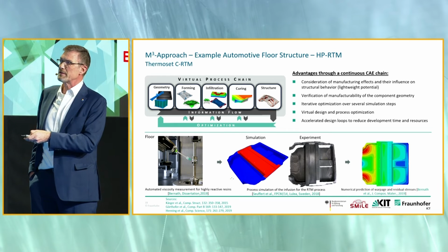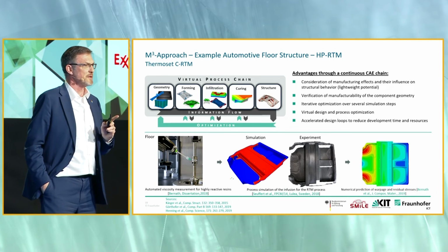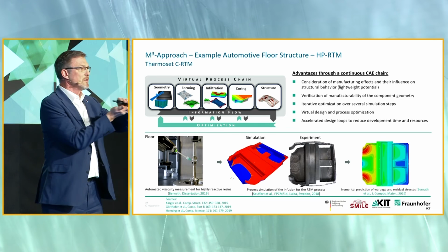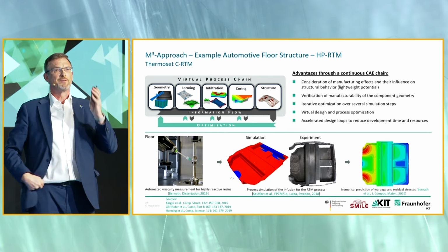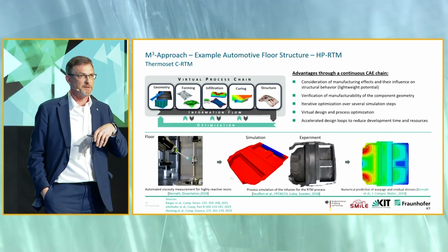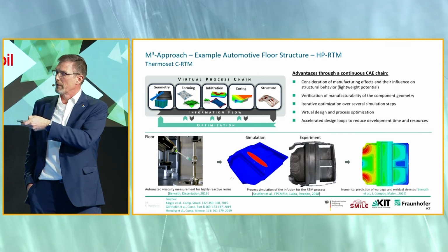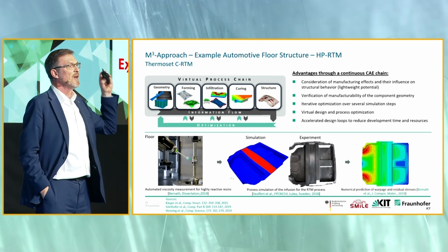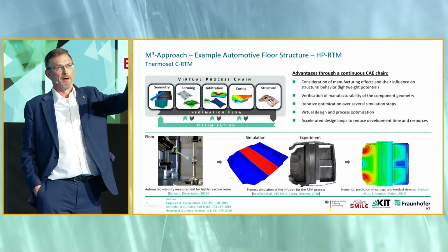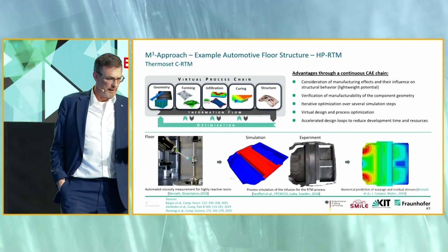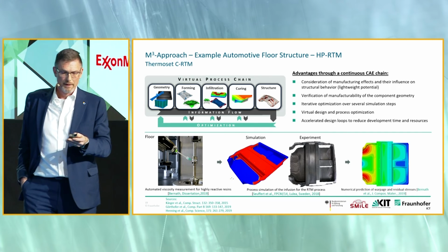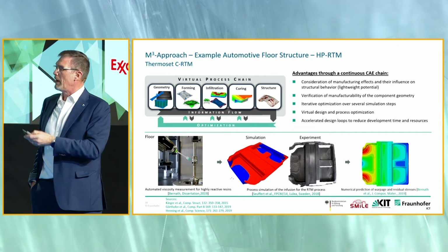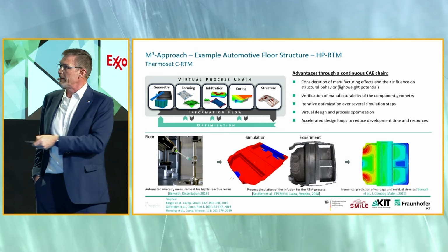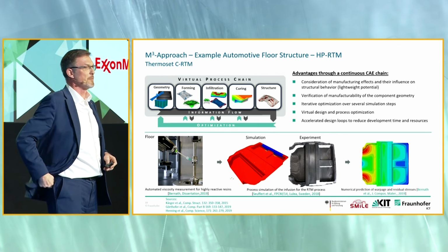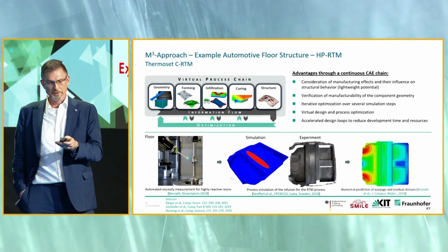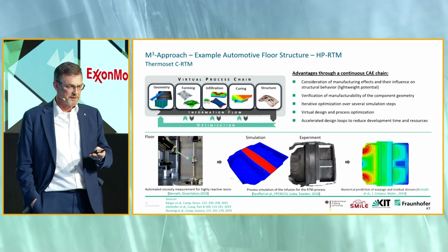And what you see here on the left-hand side is we can handle very reactive resins. Usually when you do a plate-to-plate rheology to get the data, it's very tricky because the material gels or cures already before you even start the test. Now we do online blending and online mixture, so we have developed the devices where we can mix while injecting between the rotary discs and measure from the first seconds the cure state, and can build that into our simulation. And then finally, obviously, do the curing simulation, thermomechanical simulation, which then leads to warpage prediction and helps to optimize the part in this respect.